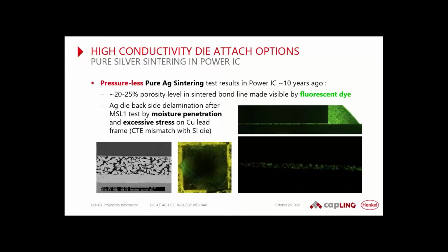But okay, I think this has been tested in power semiconductors about 10 years ago, and then that porosity level, when you don't apply the pressure, you get this kind of porosity. And especially in lead frame based semiconductor applications, this was a nice path for moisture to penetrate during moisture sensitivity tests. And then, as you can see also here with a fluorescent agent, you get moisture into the joint and in the end delamination and failures. So pure silver sintering is not a solution for semiconductor applications requiring MSL performance.